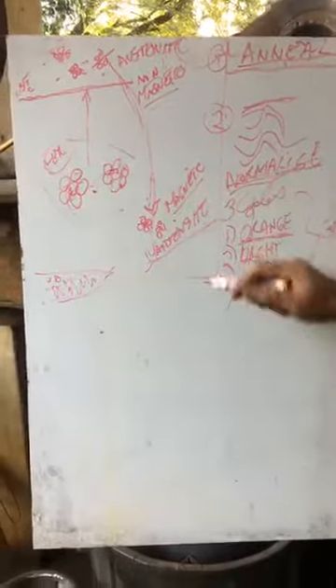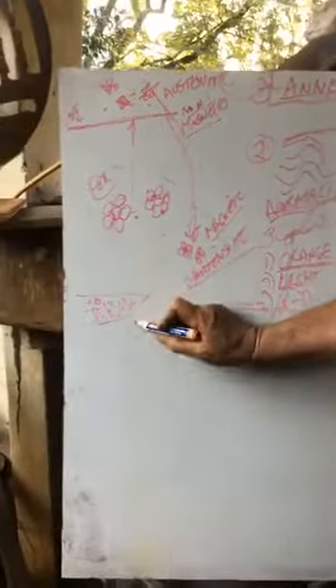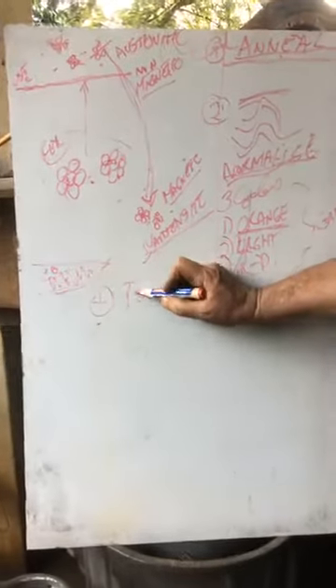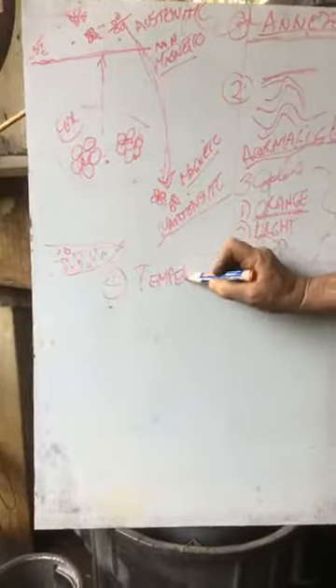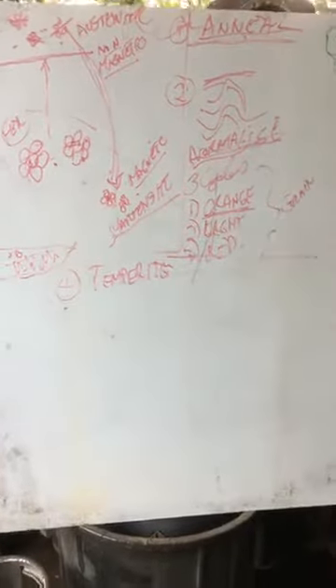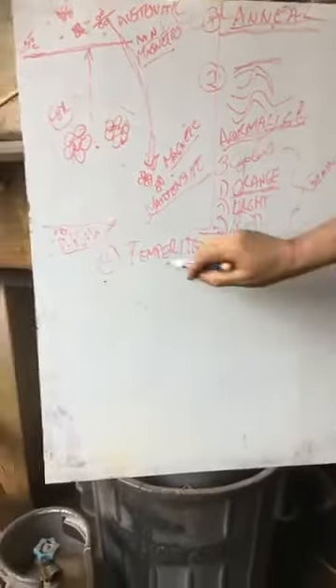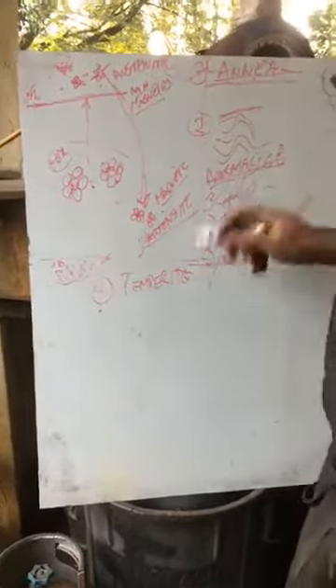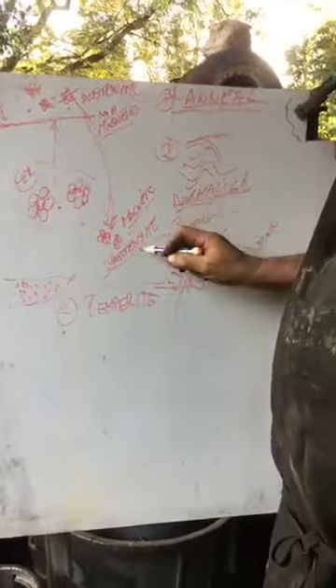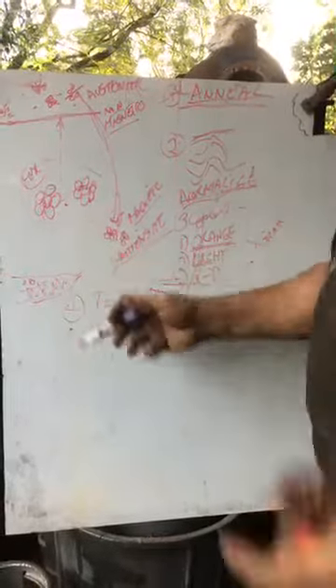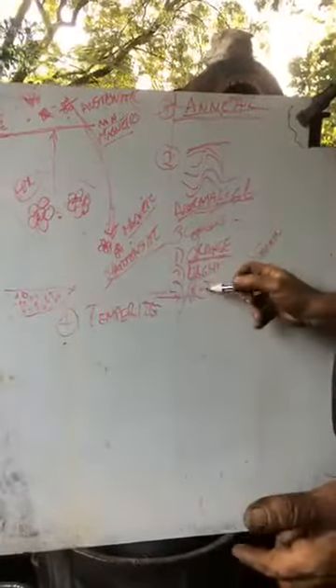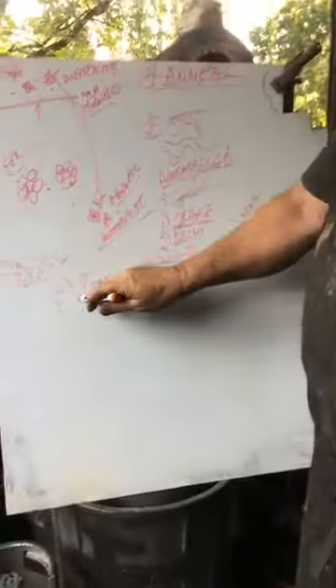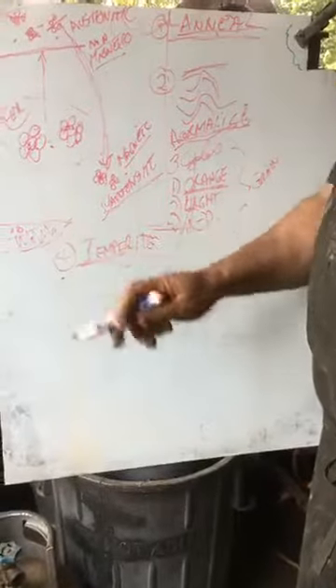After hardening, there's a 4th cycle, which is your tempering. So tempering, that's when you lose your shit if it cracks. Tempering is where you take it now. So you've basically taken it back to a file state. You can't work with a file, it's too hard, too brittle, and that's why you test your edge with a file, because theoretically your edge now is as hard as a file. That's why it's not going to bite. You need to temper it, and different steels and different smiths have different tempering cycles.